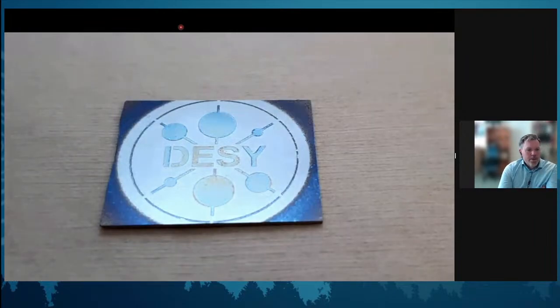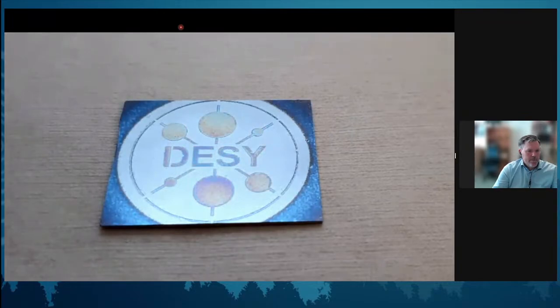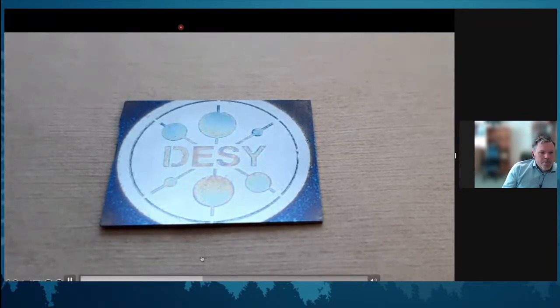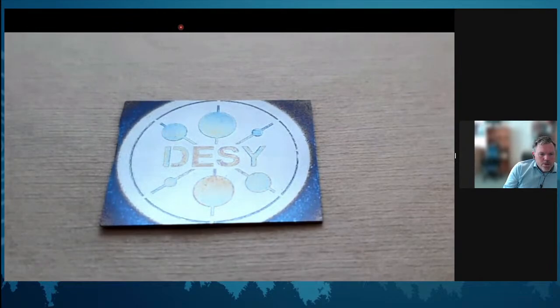The only thing that Kelvin does now is blow with his breath on this surface. So humidity just by breathing is changing the thickness of the cellulose films, and it's super fast. And it's of course related to the nanoscale structure of these materials. How fast does water come into the films?